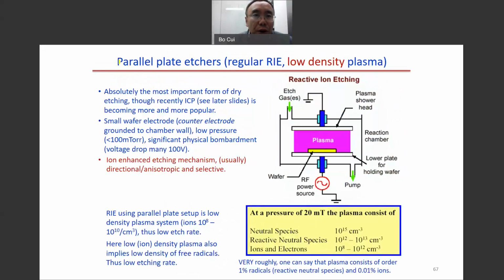The second one is called a parallel plate etcher. So here we have the top plate and bottom plate. You can see the configuration is similar to the sputter deposition, but there is one very important difference. For the sputter deposition, the target is on the larger electrode, but for the etching process, the wafer is on the smaller electrode. So the area of this electrode is much smaller than the area of this electrode. As you can see, this electrode is connected to the ground. So we know that this way there will be very little bombardment on the top, a lot more bombardment on the wafer. This way you etch away the wafer rather than etching away the top electrode.